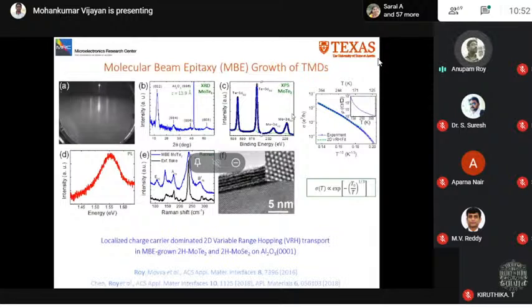So the issue in molecular beam epitaxy is that we have a very high difference in vapor pressure between the metal and the chalcogen atoms, and that's why the overall growth window becomes very narrow, and it becomes very difficult to have fine control over the flux in MBE growth of TMDs. However, for other 2D materials like the topological insulators, Bismuth-based topological insulators, MBE has proven to be one of the best growth methods. But for TMD, so far, several research groups are working in this area, including us, and we are still searching for a sweet spot where we can avoid these issues.